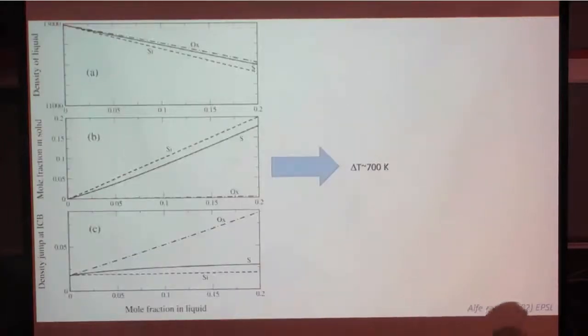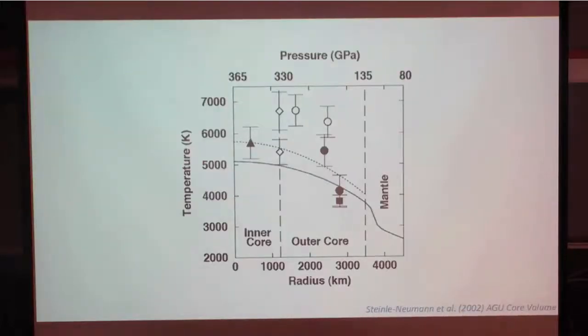The core isn't pure iron, there are some light elements in it. One of the nicest analyses, I think, of light elements in the core is this study of Alfé. What they did is they looked at the effect of silicon, oxygen, sulfur on the density of the liquid. They calculated the partition coefficient between liquid and solid, and that gives them how much of these are in the solid, and they compare that to the density jump determined seismologically. And that gives them a total amount of pairs of silicon oxygen or sulfur oxygen that can explain the density jump. And they also calculate the freezing point depression, which turns out to be 700 Kelvin. So putting all this together, you get some constraint on the temperature at the inner core boundary.